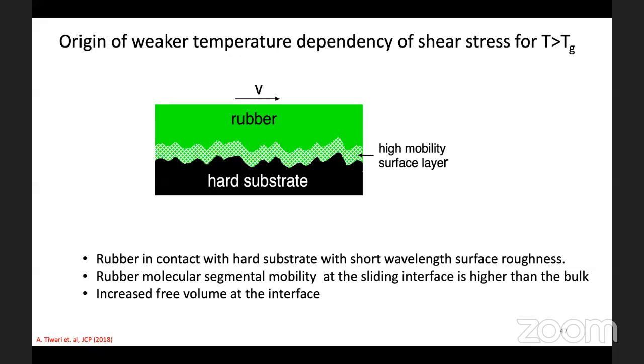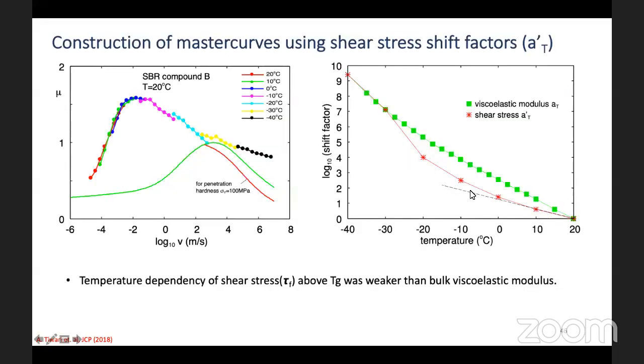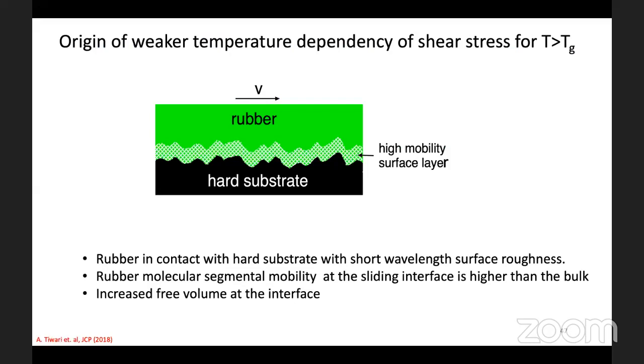for segmental mobility at the interface between the rubber and the hard substrate at short length scales. So this is the main reason why we see a low activation energy here. For the adhesive friction, the activation energy, which is of the Arrhenius type, is 1 electron volt at the surface. But in the bulk, for segmental mobility to happen and for dissipation to happen, the activation barrier energy is approximately 2 electron volts. Because of the free volume that is available at the interface between the short length scale roughness and the rubber, you have this weaker dependency.